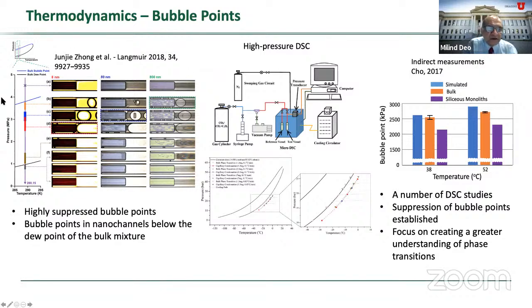And there is some evidence here. You can see this direct visual evidence that came out actually after we started the project from Sinton's group in Toronto, where they showed these capillary measurements and indicated that the bubble points actually were suppressed for this mixture. This is a gas mixture, more or less, which has, I think, some butane in it, but mostly methane and propane. And the bubble points, in fact, were so low that they were suppressed below the dew point of the bulk mixture, right? So that's what you see in this picture. The dew point curve is here, the bubble point curve is here, and you can see some of the last bits of liquids from these nano channels came out below the dew point of the bulk mixture.